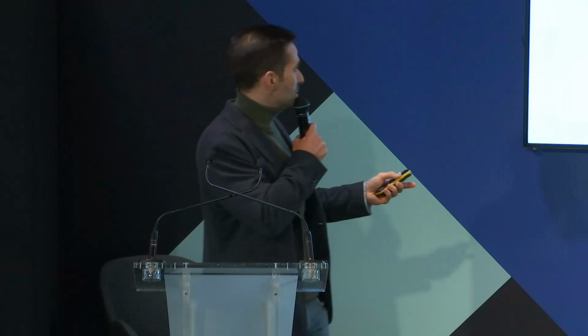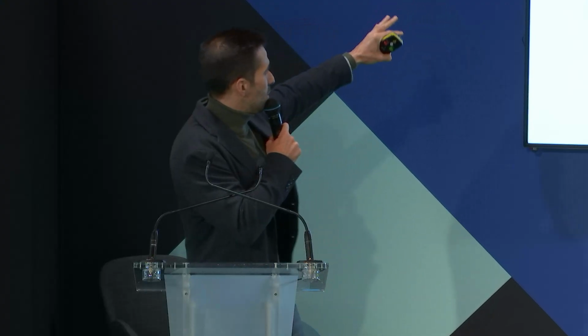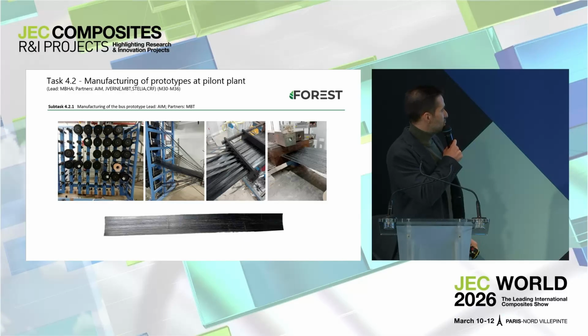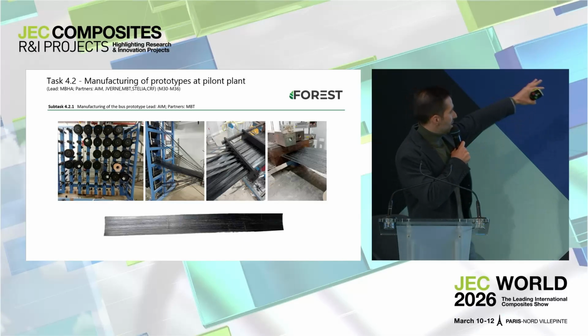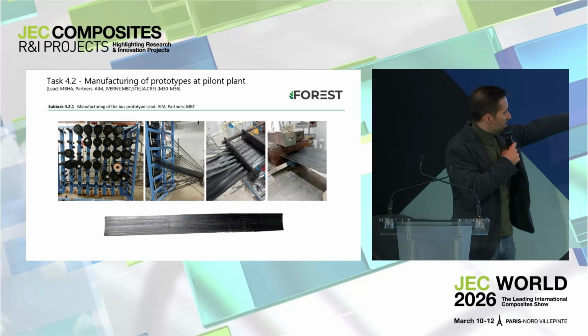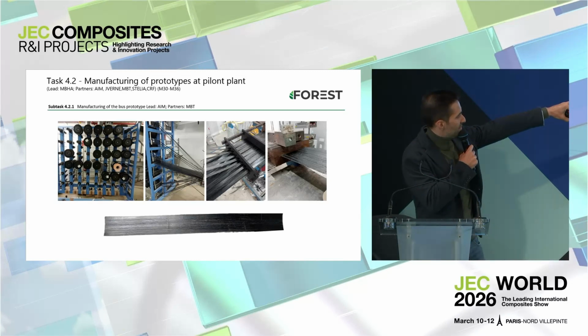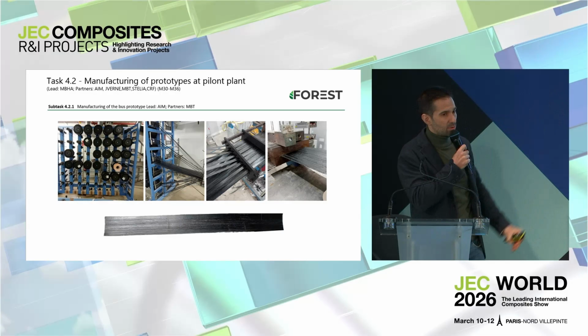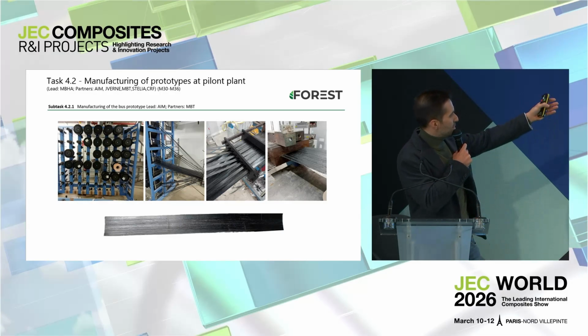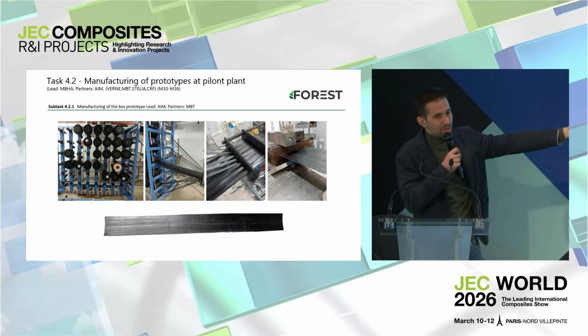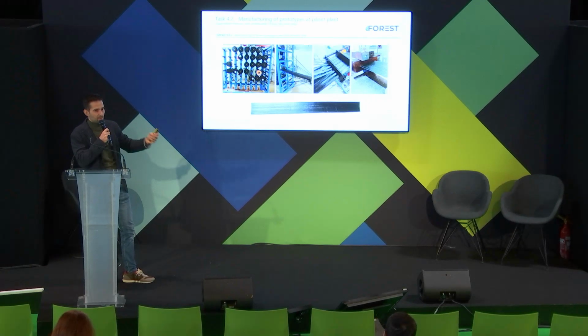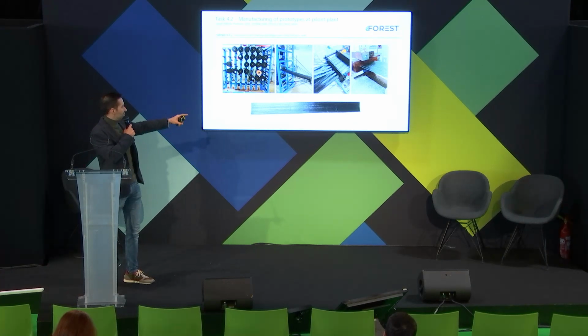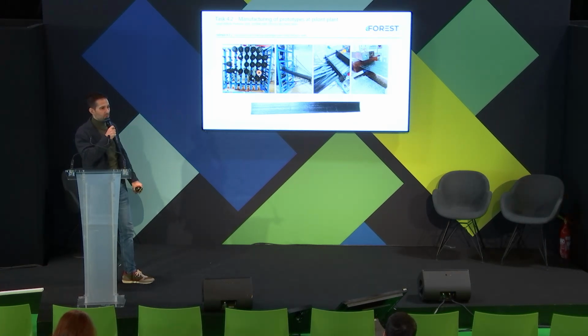Some images of the process. Here's the creel with all the bobbins, with the UD tapes, and also the organosheet. All of them are guided with the guiding system that you can see there. And then we can see the die of the mold, how the profile comes out of the mold. We don't have an image of the pulling system, but you can imagine that everything is pulling that profile from the other side. And then we have an image of the section of the pultruded profile that we can obtain, although this can be continuously produced.